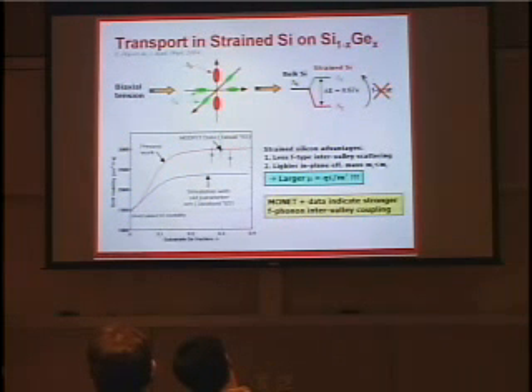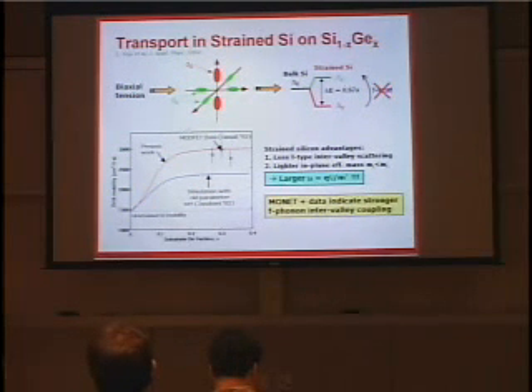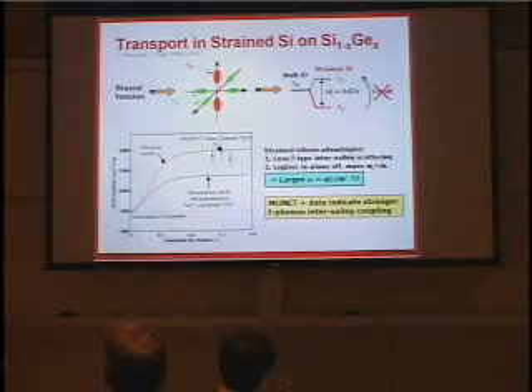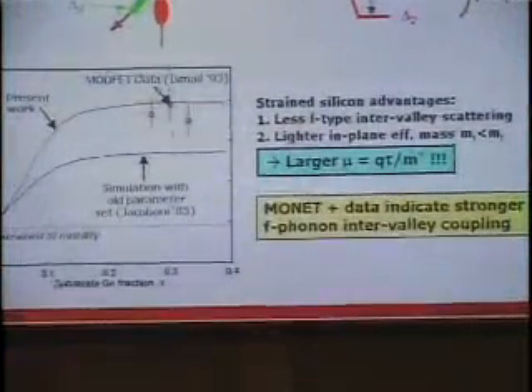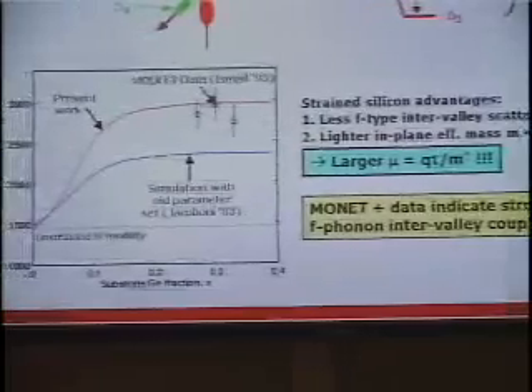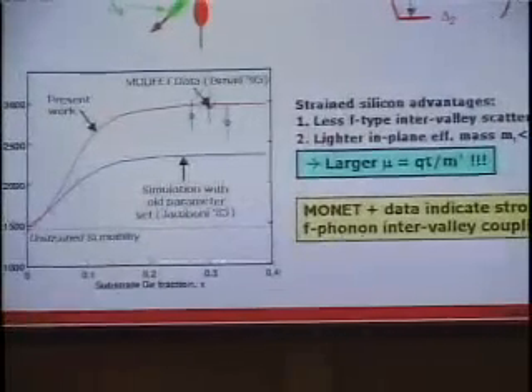The reason I'm looking at MOSFETs is because, in strained MOSFET mobility data, there's actually a lot more going on in a MOSFET as opposed to a bulk device. In a MOSFET, you have surface scattering, you have impurity scattering. In bulk, the most you have at room temperature is remote impurity scattering. So if you're really talking about the electron-phonon interaction, and you don't want your simulation complicated by other models, such as impurity scattering or surface scattering, you really should be looking at bulk data, not at MOSFET data. And so what I'm plotting there is a simulation of the present work compared to a simulation with the old parameter set as compared to this data.